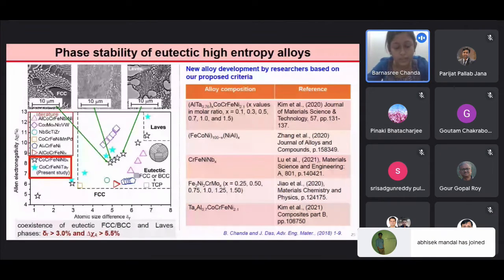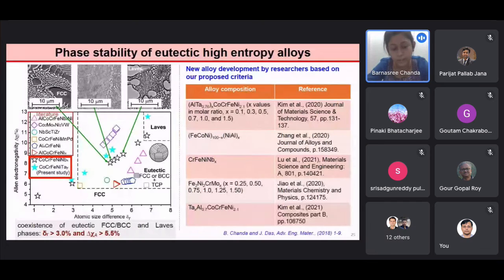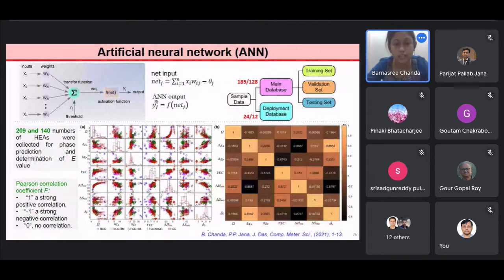The electronegativity versus atomic size difference shows that the eutectic phases are stable when the electronegativity is greater than 5.5%. So, based on our proposed criteria, various researchers have developed new alloys, and some of them are listed in the table. Therefore, further we have predicted the phases and determined the Young's modulus by artificial neural network.